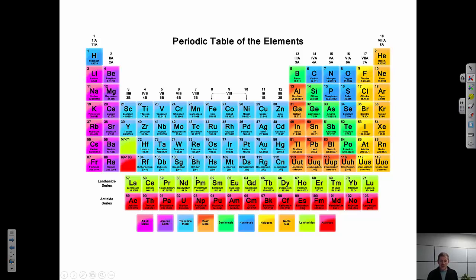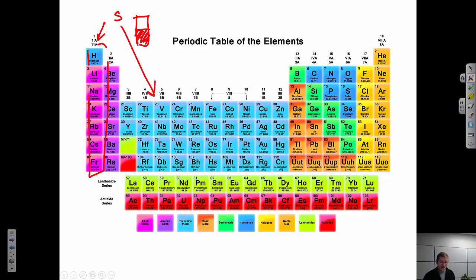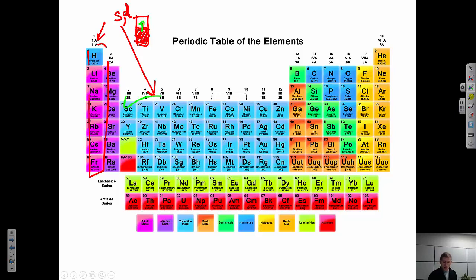Let's think about what different kinds of materials behave in those different systems. The alkali metals have a partially filled s electron — they all have one available s electron — and what that means is that the bottom band is almost always going to end up partially full. So these are metals. The same thing applies to the transition metals: in this case I have partially full d electron orbitals, and filling them up one electron at a time gives me a partially full band, meaning there are energy levels these electrons can get excited to. So these largely behave as metals.